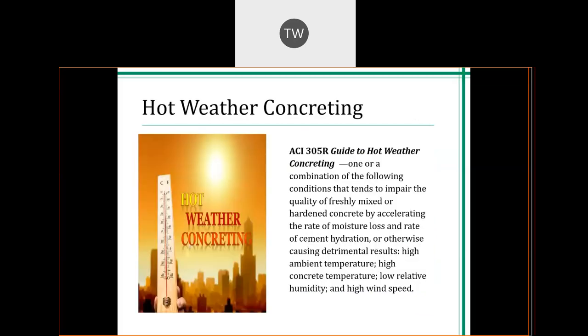ACI 305R does not provide maximum temperature guidance for concrete placement during hot weather. The real emphasis of this guide is being able to maintain proper workability without affecting your concrete strength. During hot weather, the rate of your cement hydration increases as evaporation creates issues with the workability of your concrete. The addition of water to your mix would typically mitigate these issues, but unfortunately additional water reduces your concrete strength and increases shrinkage, which then causes cracking.